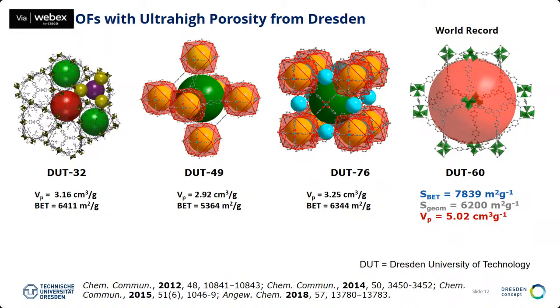But if you don't believe in surface areas, there's also the pore volume. And the specific pore volume here is 5 milliliters, 5 cubic centimeters per gram. And this is one order of magnitude higher than a traditional porous material, like a zeolite, for example, or an activated carbon, which typically can reach 0.2, 0.5 cubic centimeters per gram. So these materials are really record type of materials.